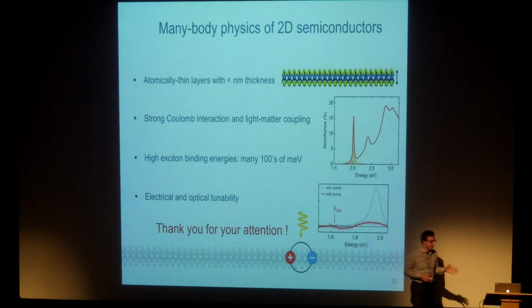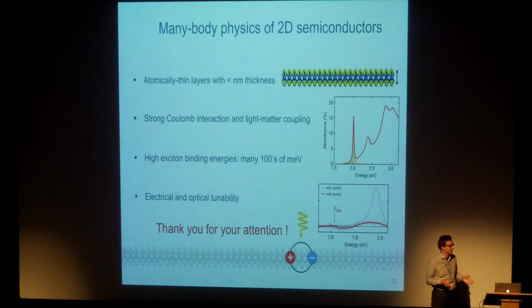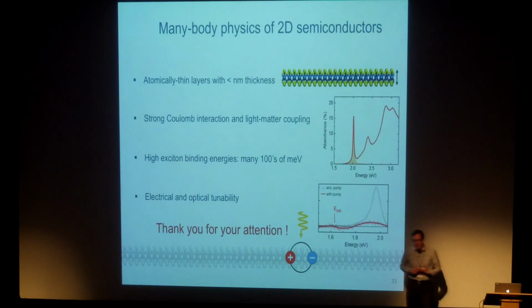So what people did, they basically provide an LED, right? So they inject both an electron and a hole. Oh no, you mean, sorry, the trion is then 2 pluses and 1 minus. Yeah, so this is possible. It's not technically possible for every flake we have because a lot of them are unfortunately doped to start with. So we need to drive our gate voltage back to get to the neutrality point. But in the flakes which are close to neutrality, you can access both regimes.